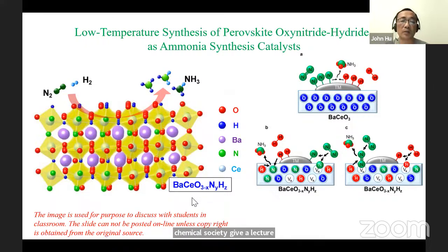This material is very expensive. And this is ambient pressure, and the temperature is only 40 degrees C. So remember, Haber-Bosch is 500 degrees C, 250 bar. They can do this at 1 bar, 40 degrees C. So the downside is you have to use this super expensive reactive material. I mean, in any chemical processing, if you want to do innovation, it's not going to be free. All right. So you reduce the temperature, you reduce the pressure. What price do you pay? You pay an economic price, basically this material. But yeah, I think they published this paper in Nature.